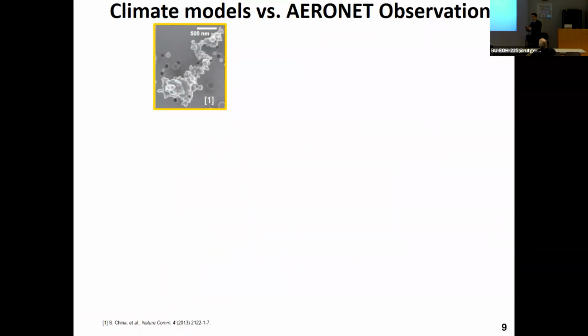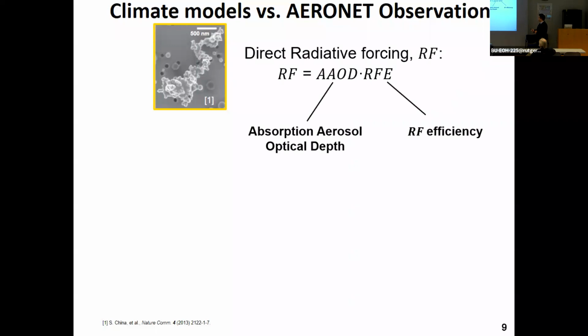Now let me get to the specifics of how one can improve such modeling of climate change. First of all, here you can see a microscope image of a black carbon agglomerate, but this time it has been out in the atmosphere for some time. So you see, we still have very porous structures, but they are coated by organics and other substances from being out in the atmosphere. Now, the radiative forcing that I mentioned earlier is just a function of radiative forcing efficiency and the absorption aerosol optical depth, as it's called in atmospheric science, which quantifies essentially the total light absorption from all black carbon emissions. This is all that I want you to keep in mind for the moment.